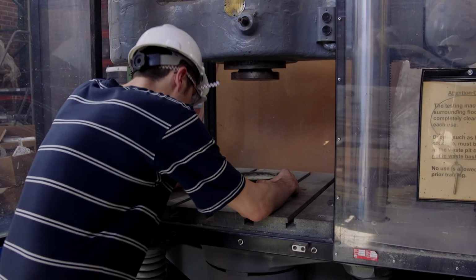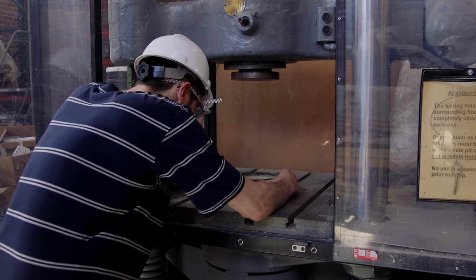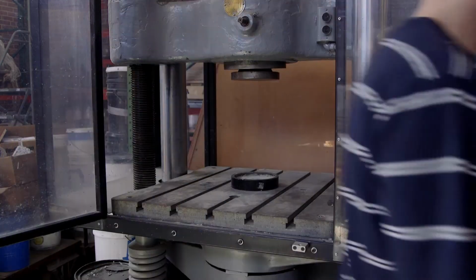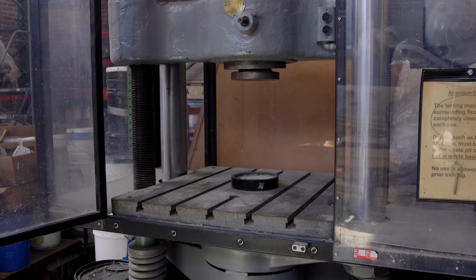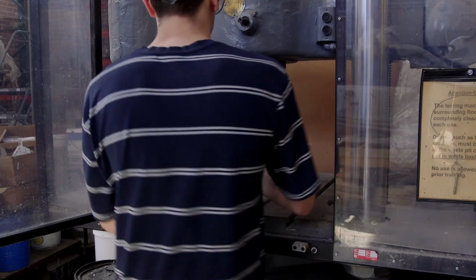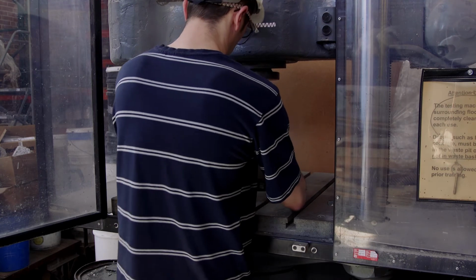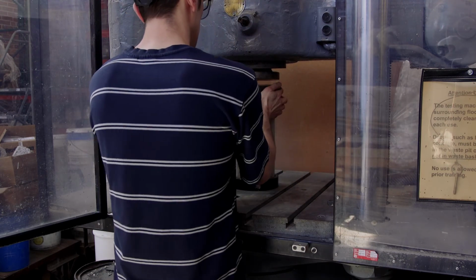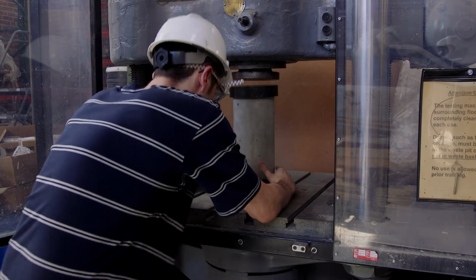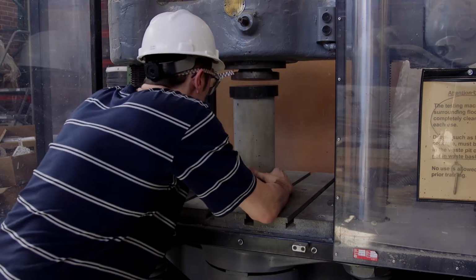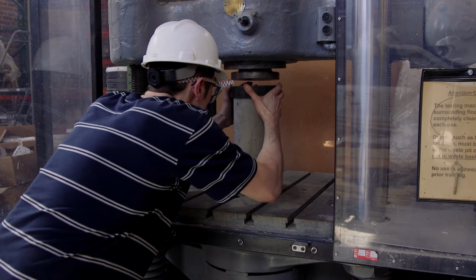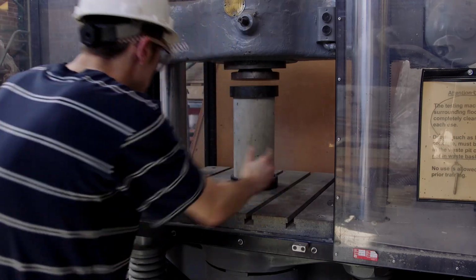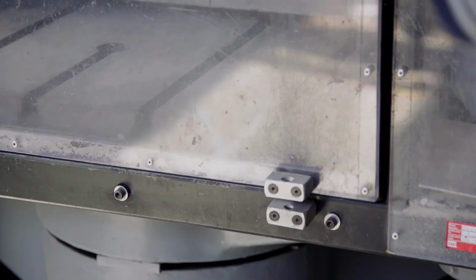With the machine off, place the 6-inch diameter bottom end cap into the device and carefully center it below the loading head. Next, place the 6-inch diameter concrete cylinder onto the end cap. Place the top end cap onto the concrete cylinder. Verify that the specimen is aligned with the loading head and then close the door to the safety cage, securing it with the pin.